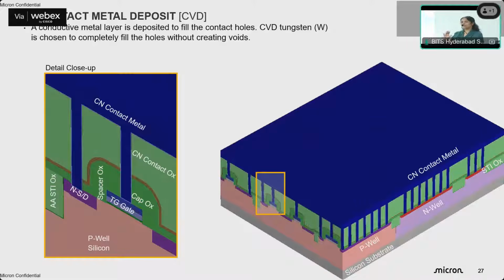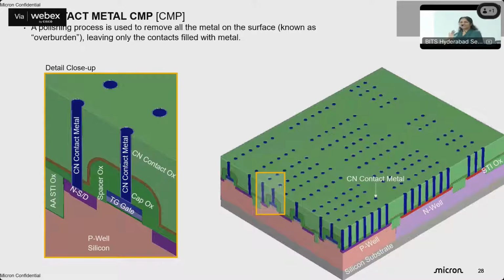So here is an example where CVD was used to fill metal into the vias, and then you do CMP, which is chemical mechanical polishing. It's like a huge machine, and they're actually grinding the wafer, and there is an end point. So the moment, for example, the oxide is detected, it will stop. It's a slurry that's grinding through the wafer. And you'll be surprised that with this brute force method, you can still very finely tune the films and the planarization of your processes.